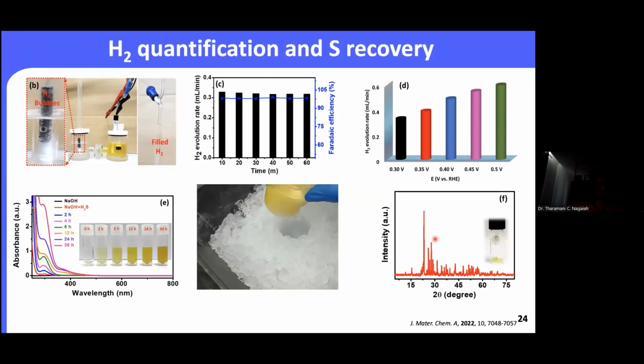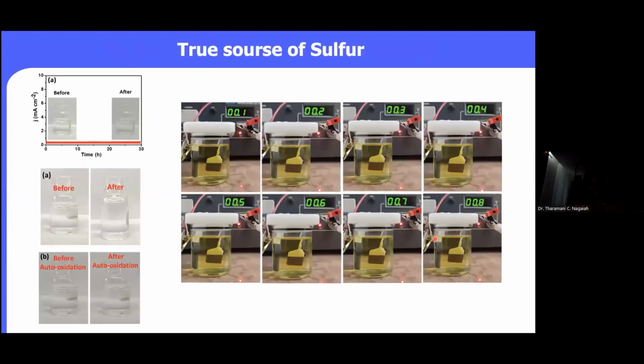This elemental sulfur can be utilized as a battery material, either as an anode or a cathode, depending on the aqueous or non-aqueous system, because the capacity is quite high in this case, especially 1,675 milliampere hour per gram. In our laboratory also, we are utilizing this sulfur, especially for the aqueous sodium ion sulfur and also the magnesium ion sulfur battery.